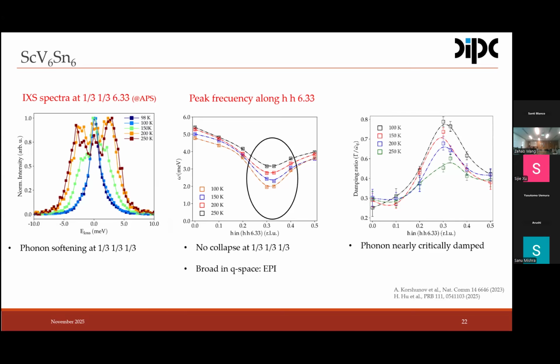The point is that the phonon does not collapse at 1/3. So the phonon broadens in a broad region of momentum space, but does not collapse. It actually remains with a finite energy at the critical temperature.